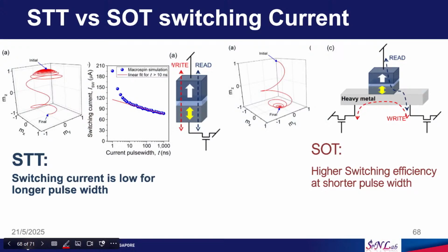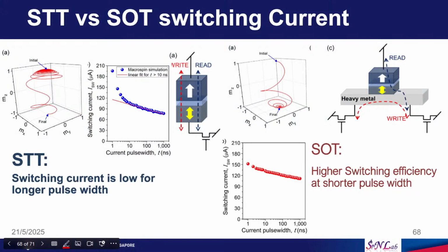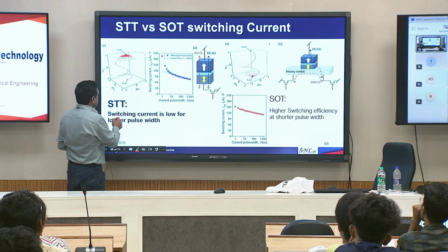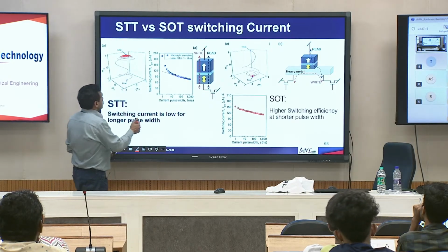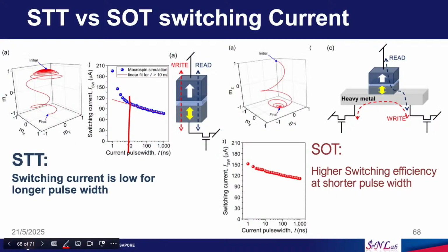Okay, so this slide summarizes everything about STT MRAM and SOT MRAM. So, in the case of STT MRAM, usually the switching speed is around 10 nanosecond. If you go lower than 10 nanosecond, you need more and more current. So, you need more energy to switch, but if you operate around 10 nanoseconds, you do not need to spend much energy. So, this is a feature of STT MRAM. On the other hand, SOT MRAM, you can operate at 1 nanosecond, without much additional energy. So, SOT MRAM helps to achieve high speed.